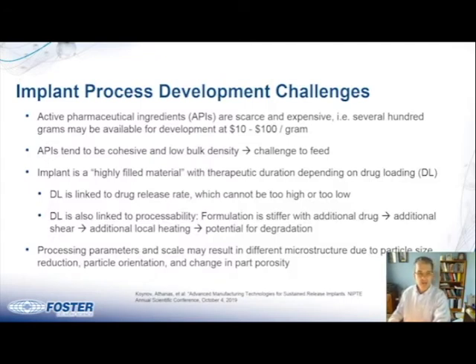So some of the challenges in developing a process for an implant. First, the active pharmaceutical ingredients are scarce and they're expensive, particularly early on in the development phase. The APIs tend to be cohesive and have a low bulk density. Usually after they're synthesized, they go through some type of milling process, and many of them go through a jet milling process so that they can get a smaller particle size and increase the surface area and enhance the drug release. However, when you have a small particle size, the APIs tend to be more cohesive, have very low bulk density, which then leads to very poor flow properties.